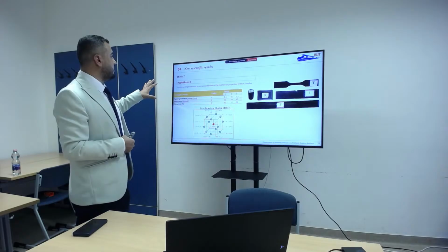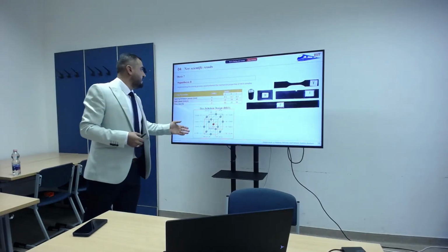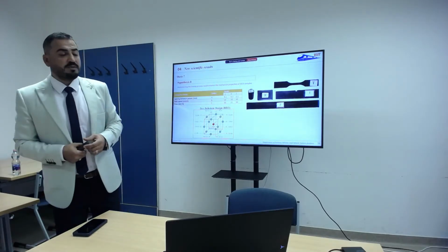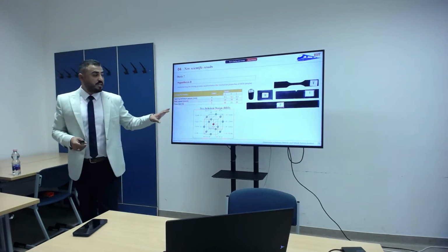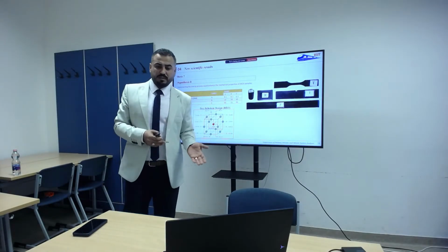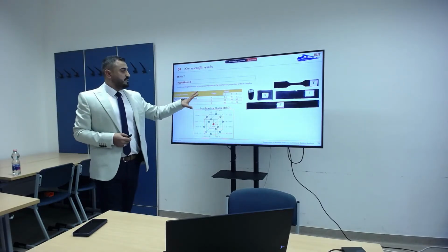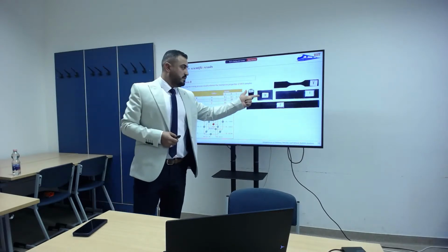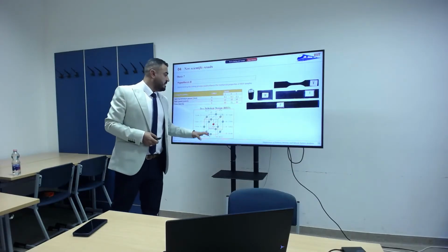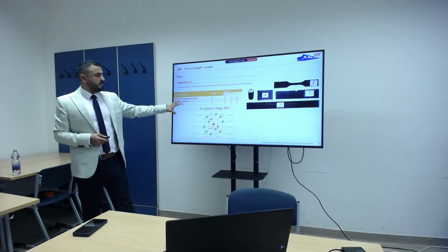For the last thesis point, thesis number 7, I investigated the proposed hypothesis that implementing ironing post-processing could enhance the mechanical properties of the material extrusion part. For this investigation, I used the Box-Behnken design, a type of response surface methodology. I investigated the tensile strength, impact strength, flexural strength, surface roughness, and compressive strength. And I used 3 parameters with 3 levels of each parameter.